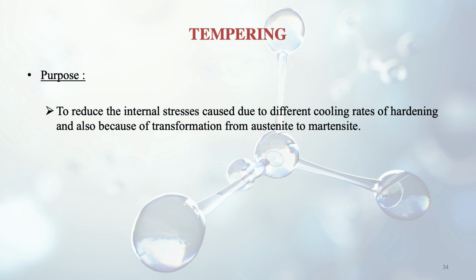These are caused due to different cooling rates of hardening and also because of transformation from austenite to martensite. Like we have taken up earlier, when austenite changes to martensite on quenching, there is possibility of cracks being developed and also internal stresses coming in. So cooling rate is very important, and due to this internal stresses come, and we can reduce this with the help of the process called tempering. So what happens in this process? Now we can see.